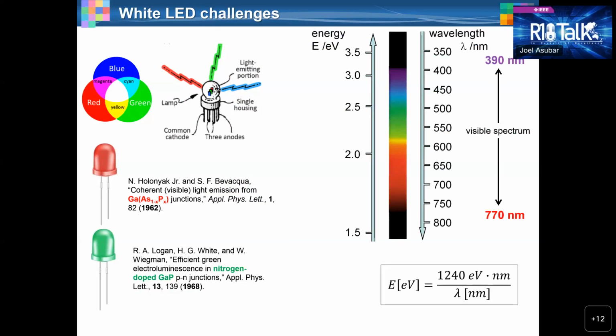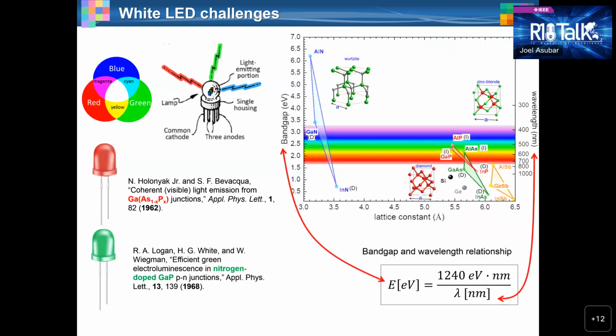Compared to green and red light, blue corresponds to a shorter wavelength. Since energy and wavelength, from this relationship, are inversely proportional to each other, a higher energy, that is a semiconductor with wide bandgap energy, is required for blue emission. That means moving away from the traditional compound semiconductors, arsenides and phosphides and antimonides, and considering nitrides, whose combination can generate blue light.